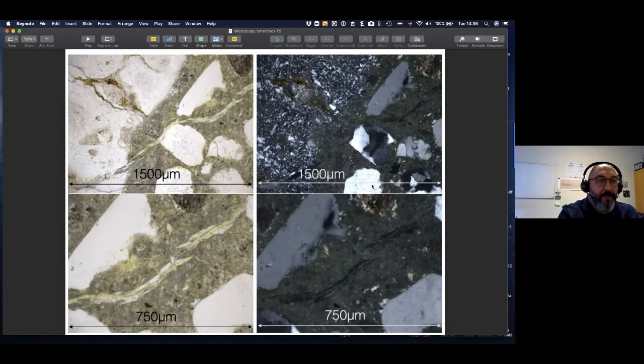Here you see another example of a cracked concrete filled with alkali silica reactions, nothing different here. Again, all I want to emphasize here is that on the left-hand side, you see the simple plain view, and the colors are generally natural. And on the right-hand side, you are observing an aggregate, and what it helps us to do here is to observe alkali reactive aggregates. We can see super tiny silica grains in our aggregate here, which tells us